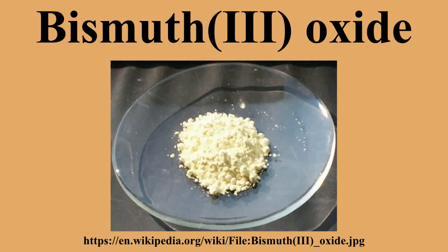Bismuth trioxide is commercially made from bismuth subnitrate. The latter is produced by dissolving bismuth in hot nitric acid, addition of excess sodium hydroxide followed by continuous heating of the mixture precipitates bismuth oxide as a heavy yellow powder. Also, the trioxide can be prepared by ignition of bismuth hydroxide. Reactions.